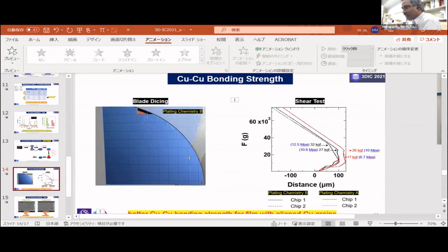And you can see none of the chips flew away. Of course, you may say that our copper film, during the electroplating itself, we do not have any copper here, so obviously it won't stick to this. But other than that, the new plating chemistry yields very good bonding strength. It withstands conventional blade dicing.